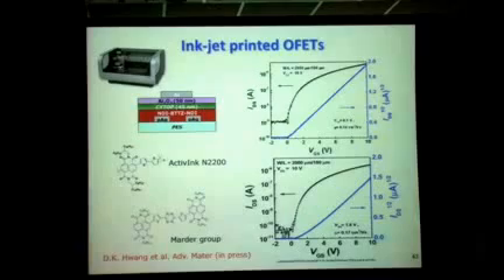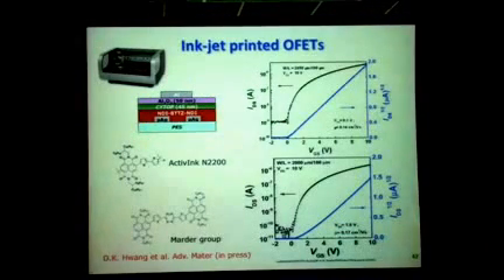Just to show that we can process these materials as inks and fabricate transistors using conventional printing techniques such as an inkjet printer - here's an example of a transistor fabricated with that inkjet printer with a polymer. Very nice transistors, with threshold voltages near zero and mobility values of the order of 0.1 centimeter square per volt second. This is with a polymer.